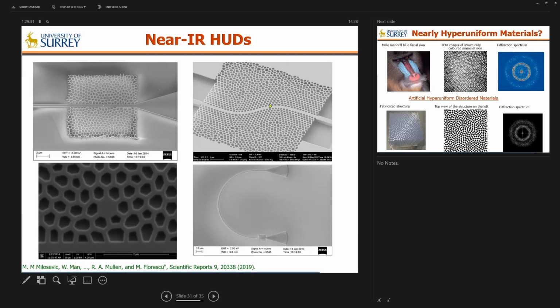And these are examples of structures that have been fabricated on these membrane silicon platforms. This is a platform in which we have a small amount of silicon in the vertical direction. It has been etched underneath, and it's in a membrane configuration without any contact with a substrate. So the light propagates solely through this waveguide channel presented here. We can also create cavities. We can put them together in a nice photonic circuit as shown here.